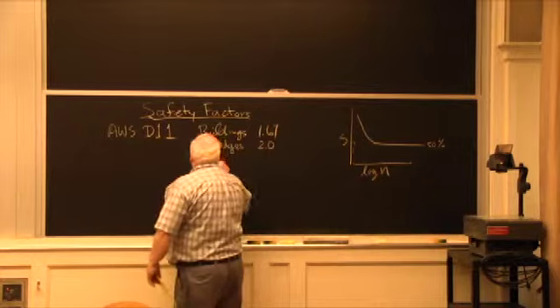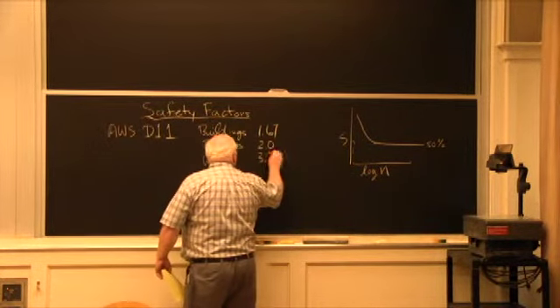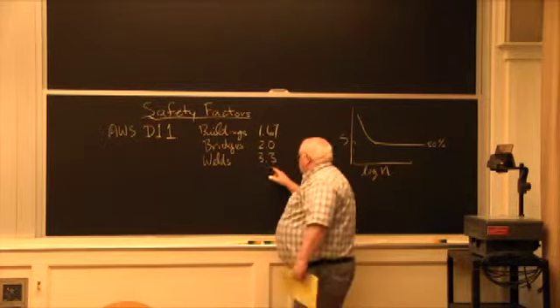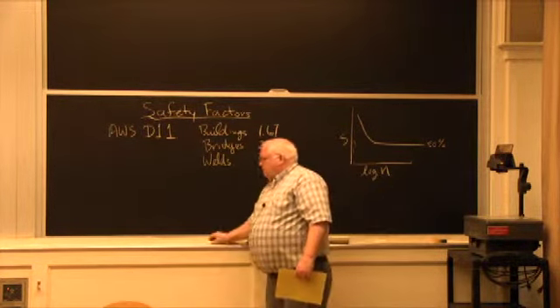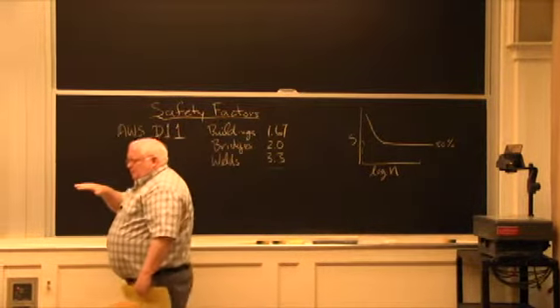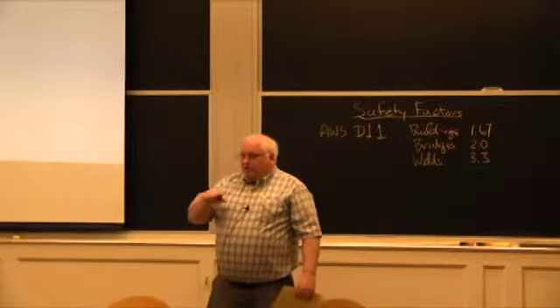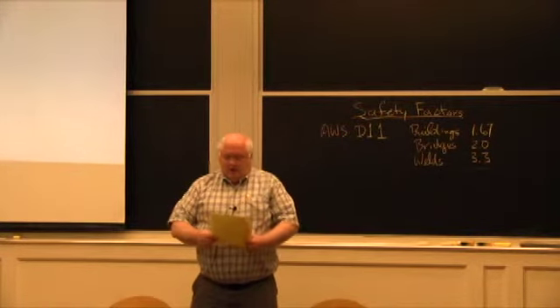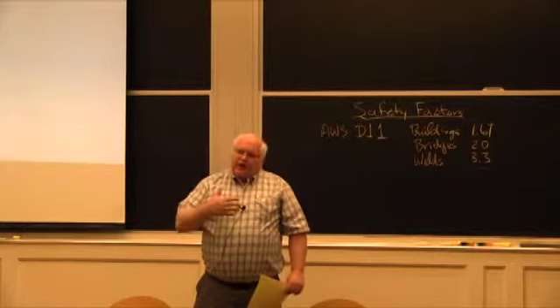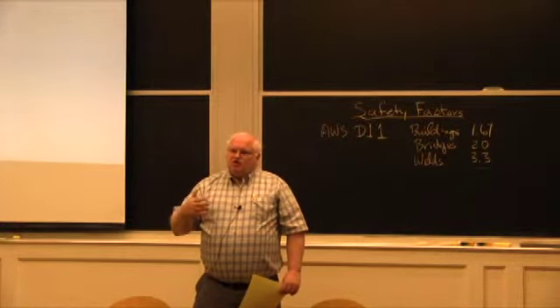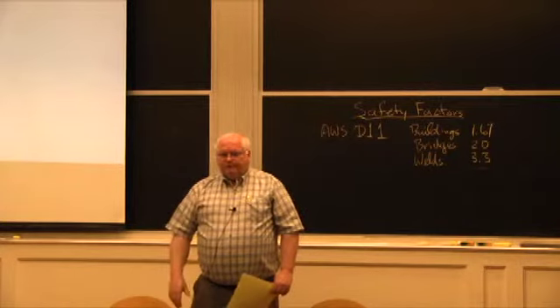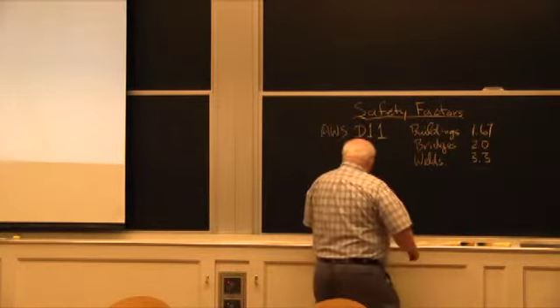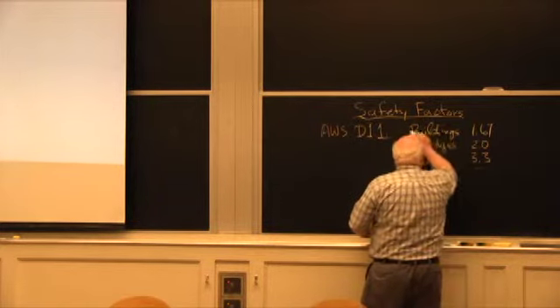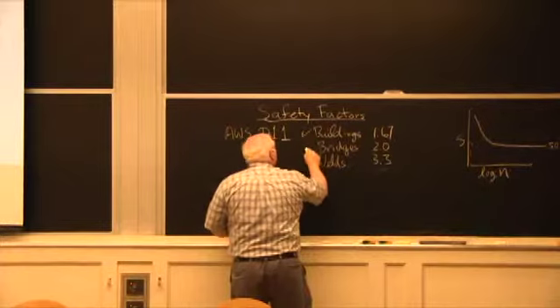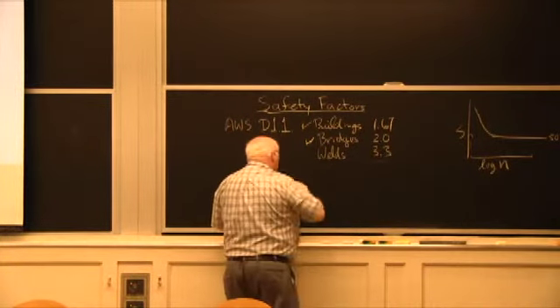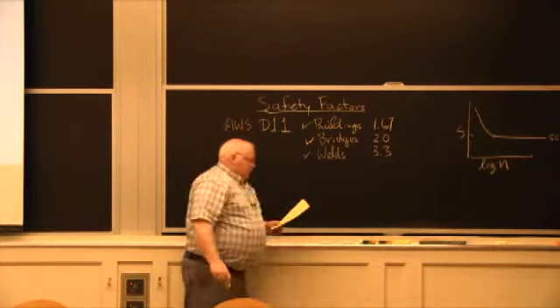Turns out for welds, most welds, the safety factor is 3.3. And that, again, is historical, but you're going to produce defects at welds. Welds are located at the most highly stressed locations, the corners. They create notches, toe of the weld, and things like that. And people just found that that safety factor on the weld is usually sufficient that you won't get failures at the weld, okay? Unless you have really big defects in the welds. So this is experience. This one, you actually can look at some scientific stress-strain curve, and this is sort of experience, and that's where they come from.